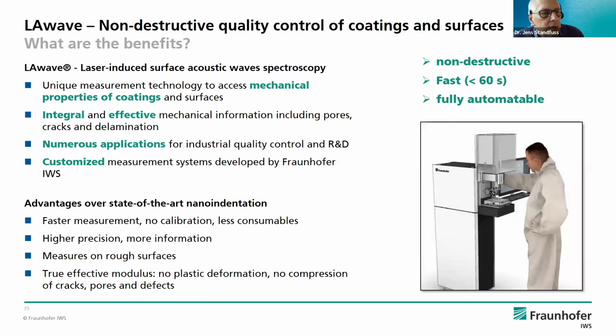At the end of the day, we can offer a complete system, adapted also to the requests of the customers. So it means you can characterize mechanical properties without destroying the part, non-destructively. We are quite fast, it's adaptable to different applications, and you can get a customized system. And the advantages compared to state-of-the-art systems like nano-indentation is you have a faster measurement, no calibrations, less consumables, and you get more information with a higher precision.